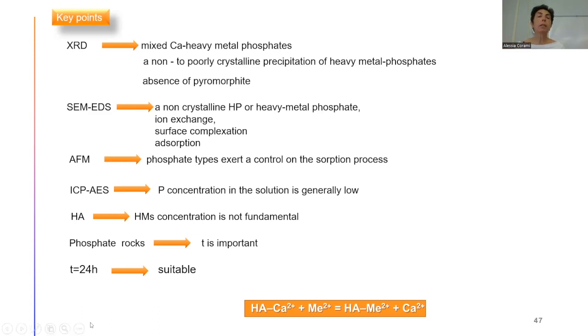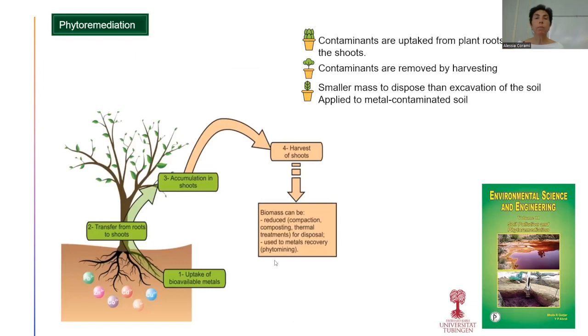From the ICP-AES, we observed that the amount of phosphate at the equilibrium is low, so it means phosphate could be really stable, also if we change the pH condition in the environment. The other point is that the initial concentration is not important; what is important is the internal competition and the time. Time is fundamental. Generally speaking, we can say 24 hours are important to get a good immobilization of these metals. Then I moved to Germany and I started to study phytoremediation.